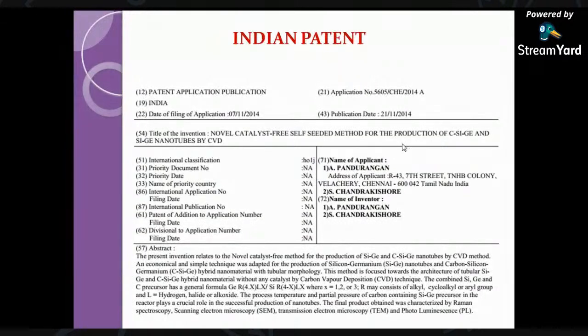We were trying to create a material without a catalyst. So it is a novel catalyst-free method for the production of carbon silicon germanium and silicon germanium nanotubes by CVD. The novelty of this patent is that normally silicon forms wires, and silicon and germanium form wires. But in this case, we are getting a nanotube structure where you can dope silicon, germanium, and carbon in one tube. Here we have silicon and germanium. And one more advantage of this patent is that we don't use a catalyst for the synthesis of these materials.